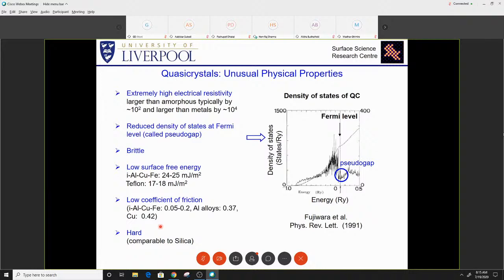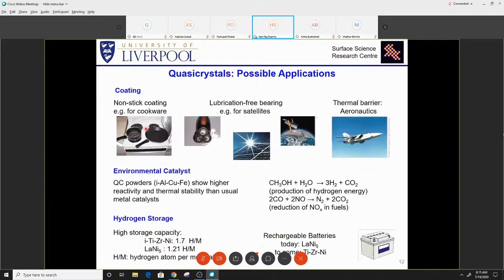Coating materials. Some quasicrystals have shown high stability and high reactivity in important chemical reactions, such as the production of hydrogen energy. So they are important from an environment and energy point of view. The potential for hydrogen storage has also been tested in some quasicrystals, and we found that they have a high storage capacity. But again, it is hard to release the hydrogen.